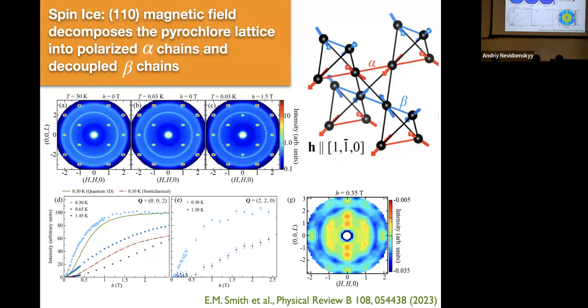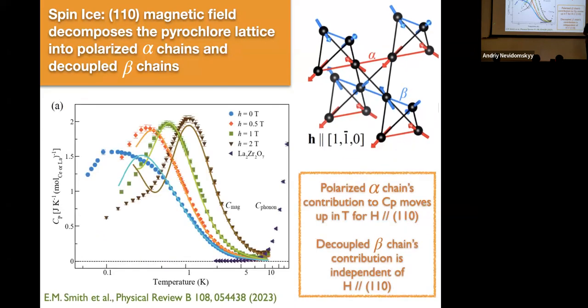Okay. And its heat capacity, I mentioned I was going to come back to this. The heat capacity in a 110 field also behaves as you would expect a spin ice to behave in a 110 magnetic field. This is the heat capacity on a logarithmic scale now. So this is in zero field here in blue, and we can describe it quite well with that theory that I was showing you. Okay?